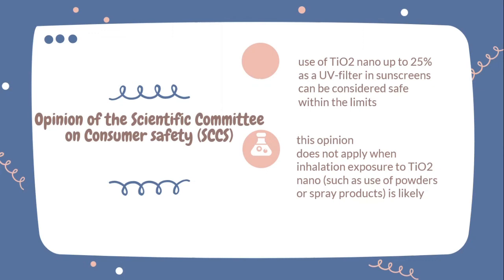And it needs to be emphasized that the SCCS, which is the Scientific Committee on Consumer Safety, conclusions have been drawn from a very select group of cosmetic products based on only one type of titanium oxide material, which is pigmentary, anatase, and surface treated. So it may not be clear whether this conclusion would be applicable to the use of pigmentary titanium oxide materials in other similar types of cosmetic applications that may be on the market.